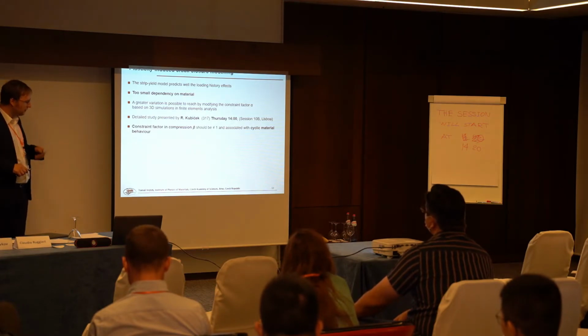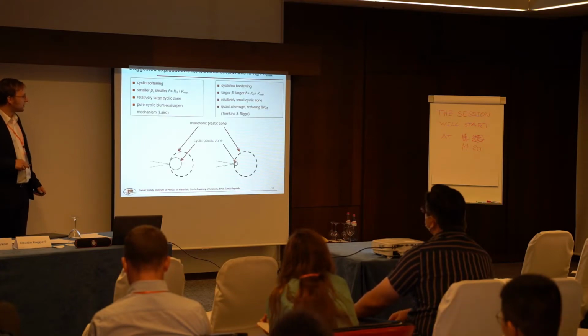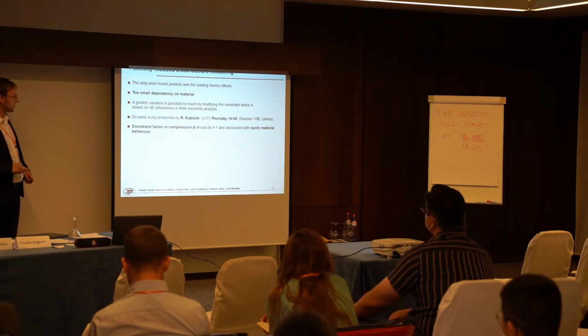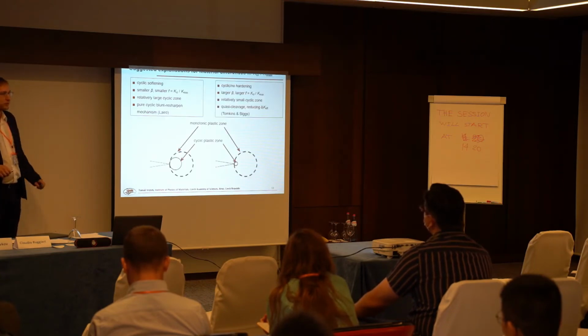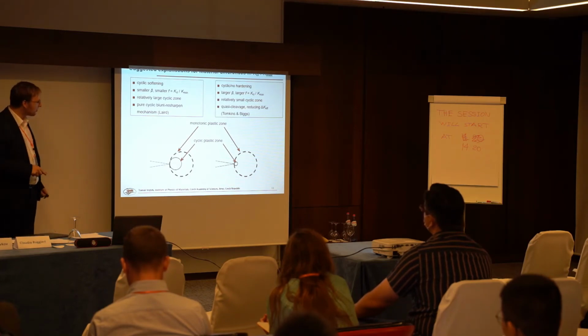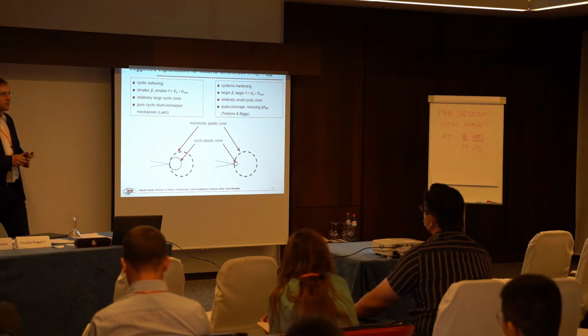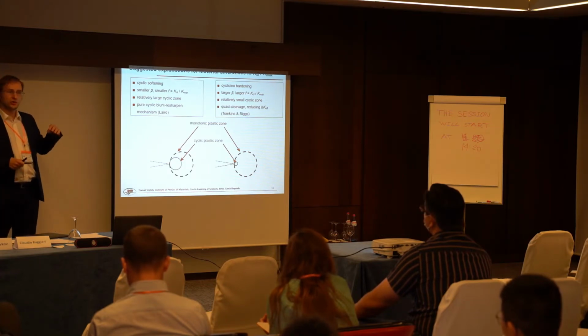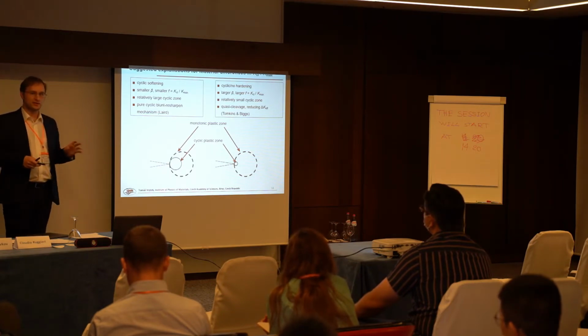So there is some material model according to the stress strain curve. And the idea how to take into account cyclic material properties is by changing the constraint factor in compression, beta, that should be different from 1. And here's the idea. When you think about the plastic zone ahead of the crack tip, it has a certain size, and then we have fatigue loading and cyclic loading. So apart from the monotonic plastic zone, we have also the cyclic plastic zone.